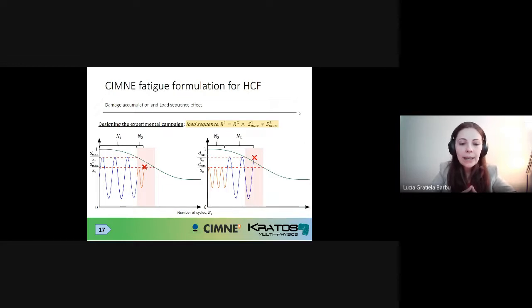Now, when you start to do this type of analysis, an important thing that you have to make sure is that you are quantifying correctly the change in the material properties for each different block or each different cyclic loading. For instance, here in the first image, we have a determined blue cyclic loading with a level of maximum stress, which is S max 1. And after that, we apply cyclic loading, which has a lower level of maximum stress, although we maintain the same reversion factor. In the image on the right, we are switching the ordering between these two. And in order to be able to account properly for what would be the fatigue life resulting from these two different load combinations, you need to make sure that you are quantifying correctly what's the change in the material properties for the first type of loading, for the second type of loading, etc.